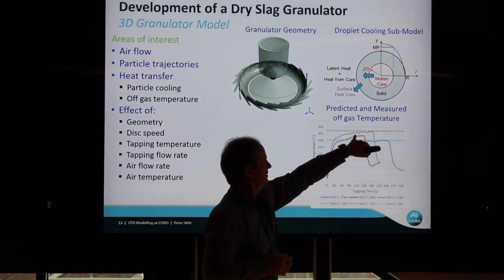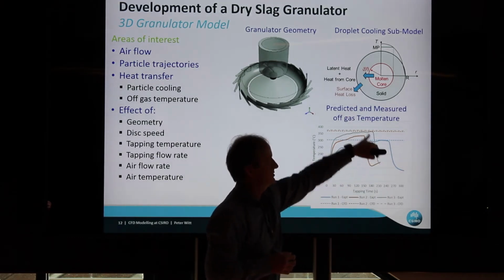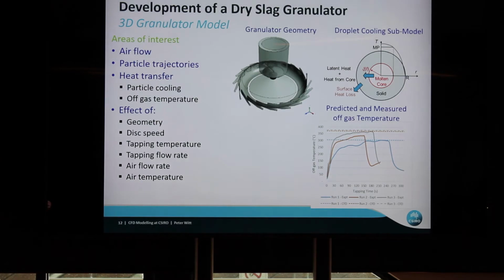And you can see these are fairly short tapping tests, but we can get a reasonably good idea of what the heat production is so that we can then look at how changes to the geometry, disc speed, tapping, etc. will affect performance, and look at how, as usual when you're doing something like this, you have to do a number of changes to the prototype design. So we're able to model those to try and help the experimental scientists look at design changes and how to improve performance. As part of the work, we developed a model for droplet cooling and built that into the particle tracking.